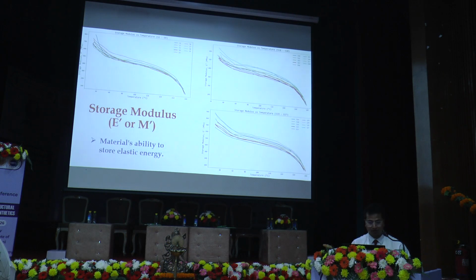I used nylon carbon filament, and with the FDM 3D printer I printed composite samples. Then I performed dynamic mechanical analysis in 3-point bending mode, and then I took that data and applied machine learning models to optimize my printing parameters and to know which parameters affected the dynamic mechanical properties more. So these were the curves, storage modulus versus temperature. Basically I printed 27 specimens with different printing parameters.